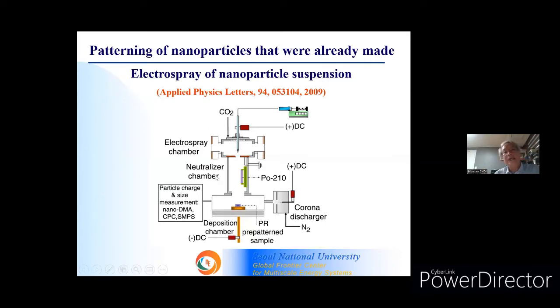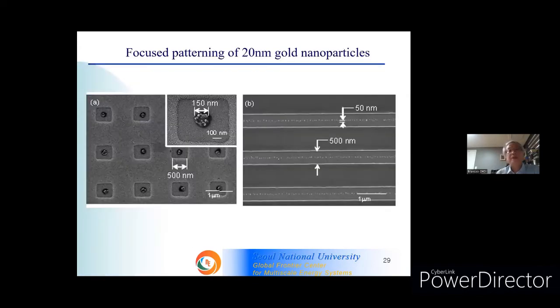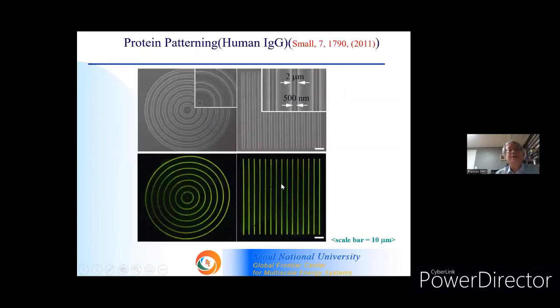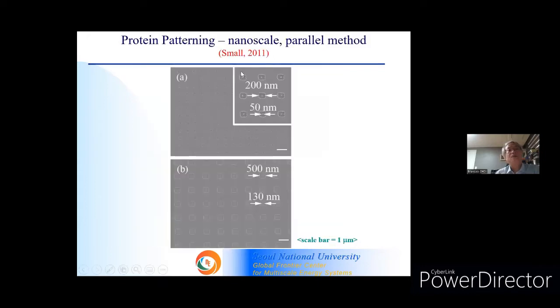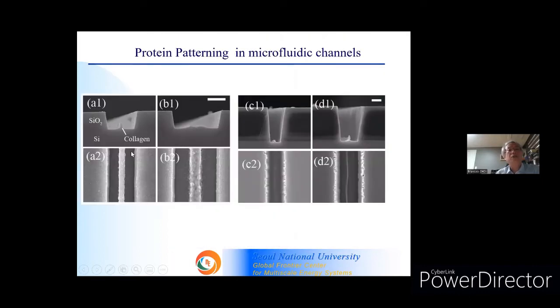So in this case, we used a neutralizing chamber first to lower particle charge, and then we successfully patterned nanometer scale line patterns or dot patterns. Even protein can be patterned, or protein nanoarrays having 50 nanometer scale, or you can introduce collagen protein within a microfluidic channel using our method.